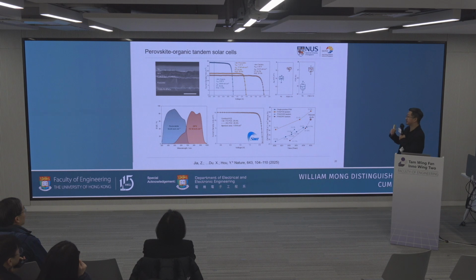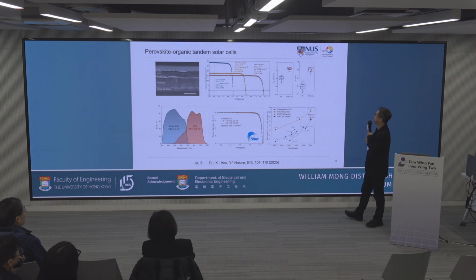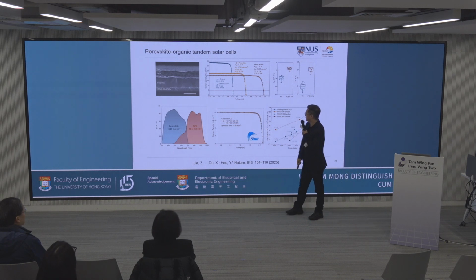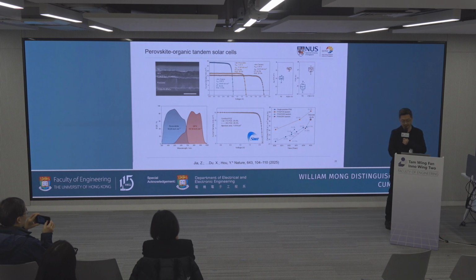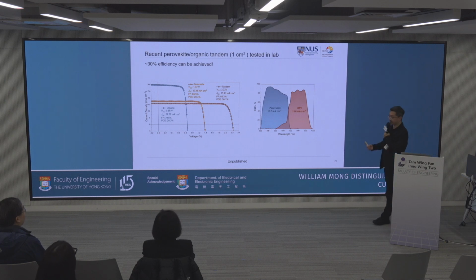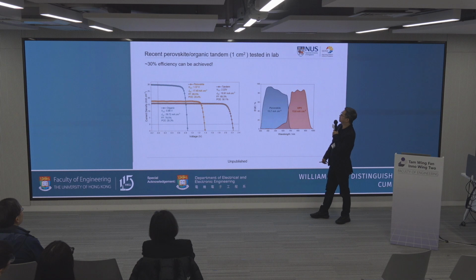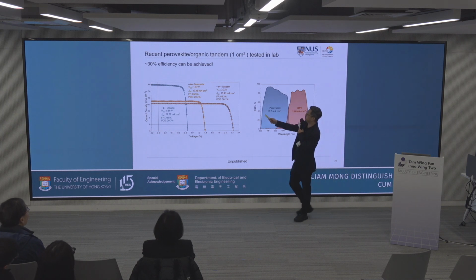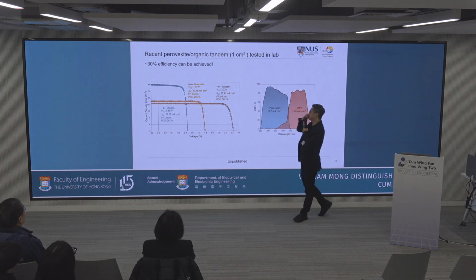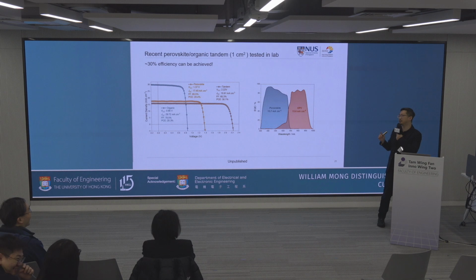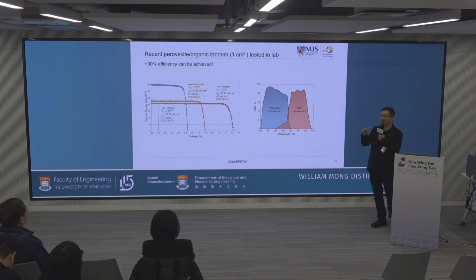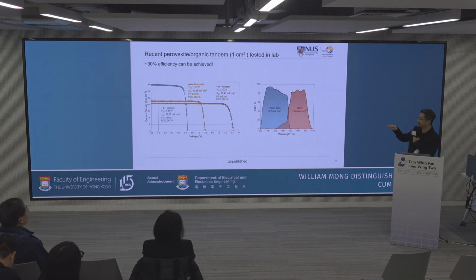And okay, so this is the solar cell performance. It's about 27%. For 1 square centimeter, certified 26%, and it's getting close to the perovskite tandem, but there's still a 1%, 2% gap. And in this paper, and quite recently, not published yet, in the lab we also got an even better device. We are certifying this one, and this efficiency is around 30%, 1 square centimeter perovskite-organic tandem, measured in-house. It's not certified yet. We certified one 2 months ago, and the result is about 29. It's not 30, there's a 1% gap, and we want to make it better. But even at 29 certified, I think it's quite close to the perovskite. Perovskite at 1 square centimeter is also 29 something. So I just want to say that this technology, in terms of efficiency, can be close to the perovskite.